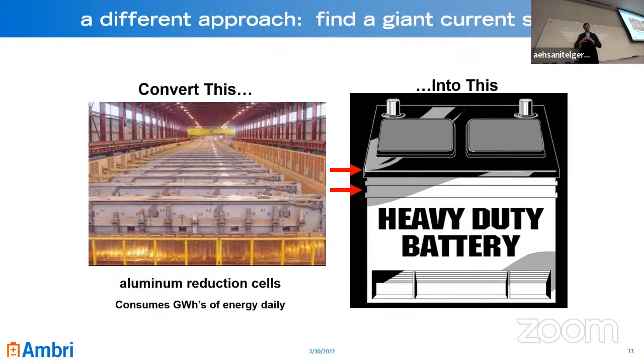Aluminum is produced through this kind of crazy high temperature process that operates at close to 1,000 degrees Celsius, uses molten cryolite, which is one of the world's most corrosive materials, into which you can dissolve aluminum oxide, which you mine out of the ground. And then you pump current through it using these massive carbon electrodes and a carbon floor. Through that process, you convert the aluminum 3+ ions that come from the aluminum oxide, and you pump electrons into them, creating aluminum metal, which then deposits underneath and pools in this big, thick layer.